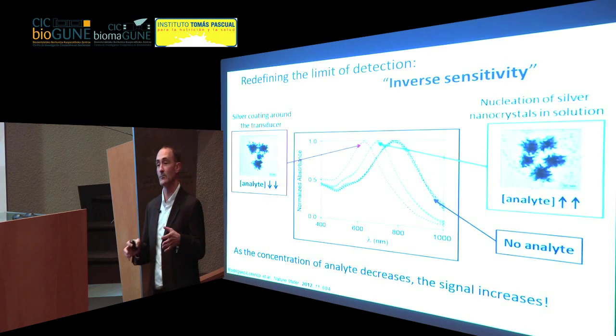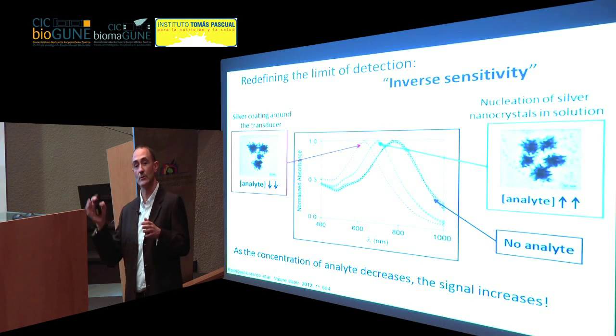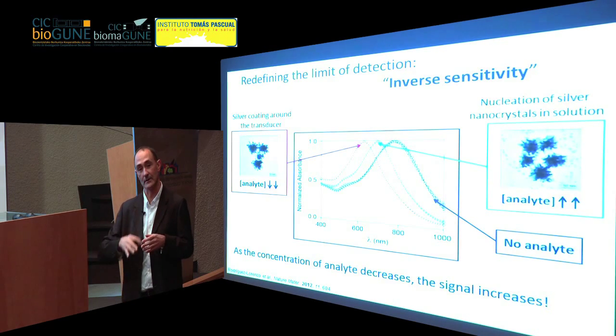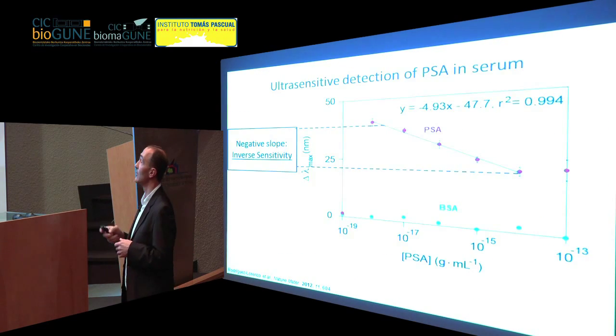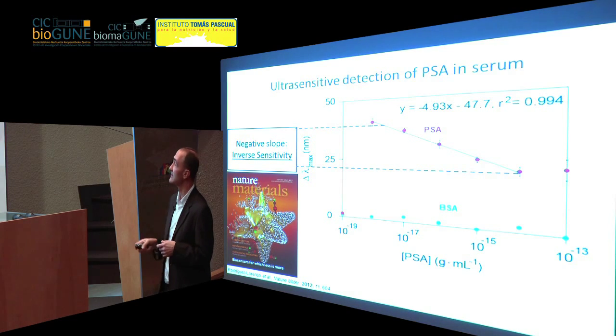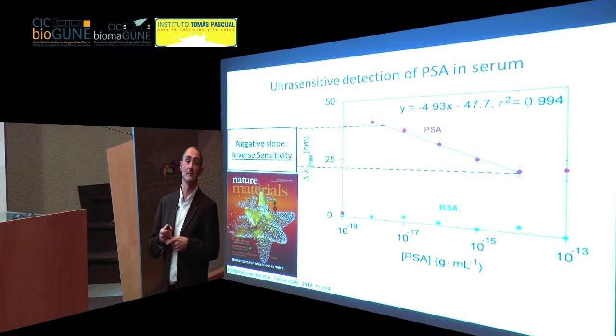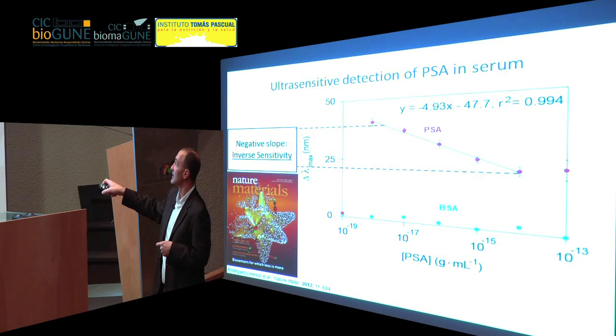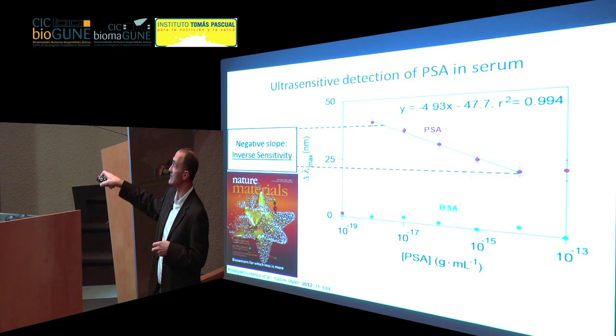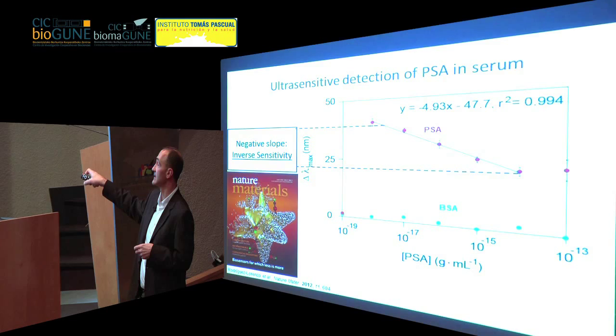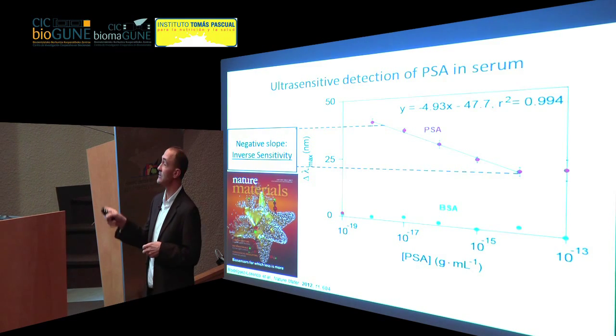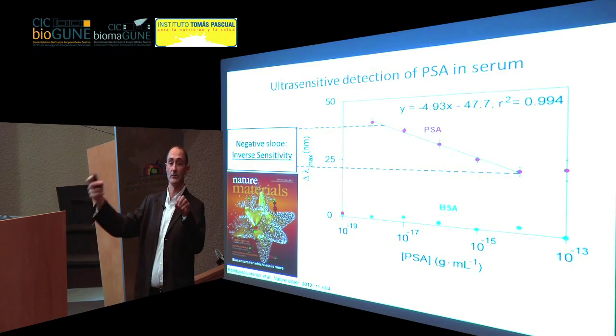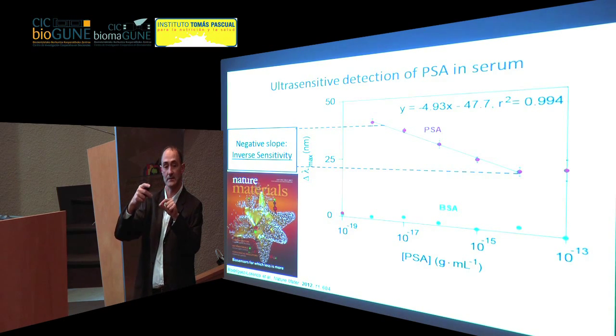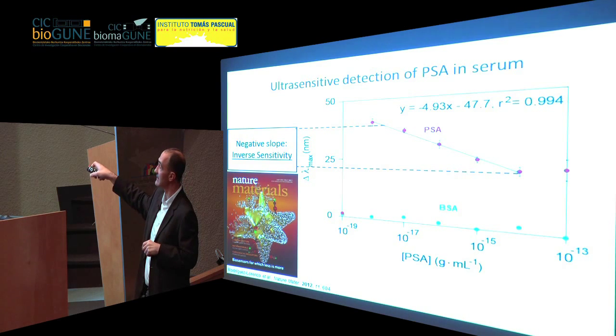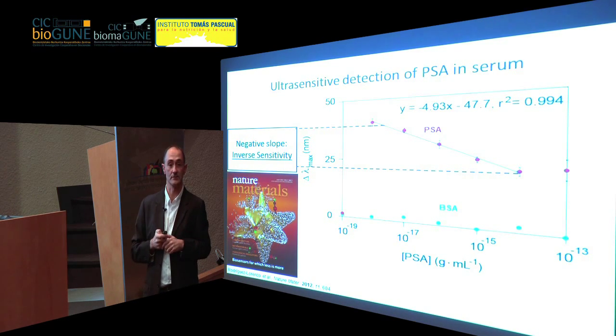So this is a completely new way of thinking, because here, when you reduce the amount of the analyte, you increase the signal. So you can go to extremely low concentrations. 10 to minus 18 was the minimum we could detect. So as you see here, also in the presence of a non-specific antigen, you don't see any effect in the optical response. So only when the PSA is coming to bind to the initial antibody and then the second antibody is also being attached, we can carry out the reaction, and the signal increases for lower concentrations of the analyte.